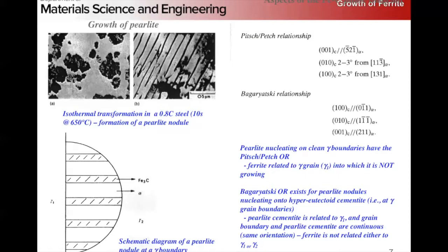And this, in general, will be an incoherent, high energy or high misorientation boundary, right, that has significant mobility. So the coherent interface would be a relatively immobile interface. This interface would be able to grow.